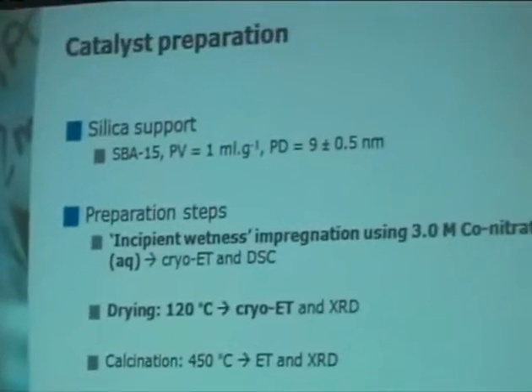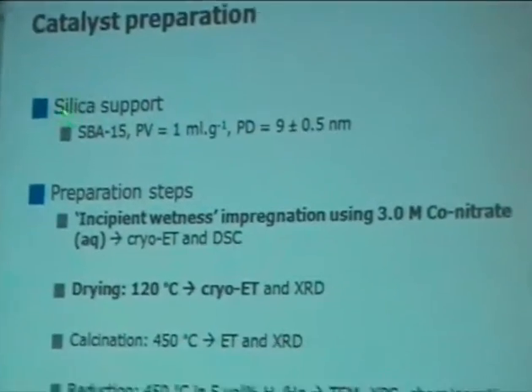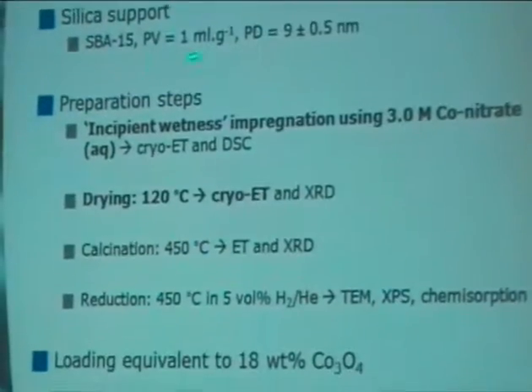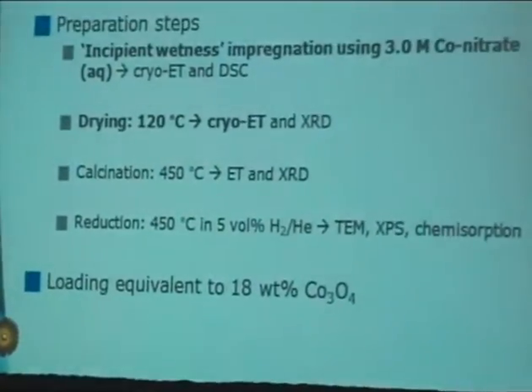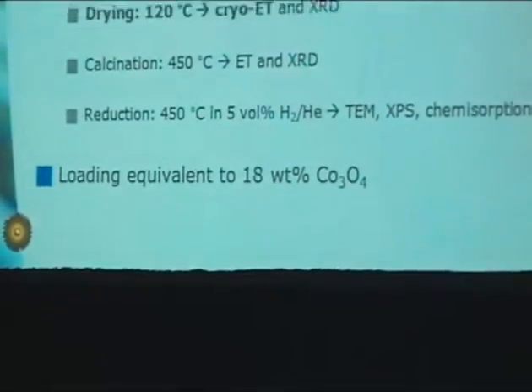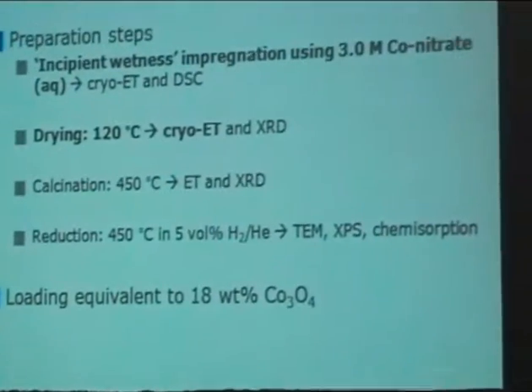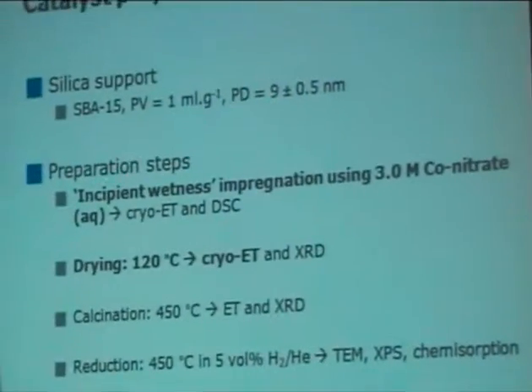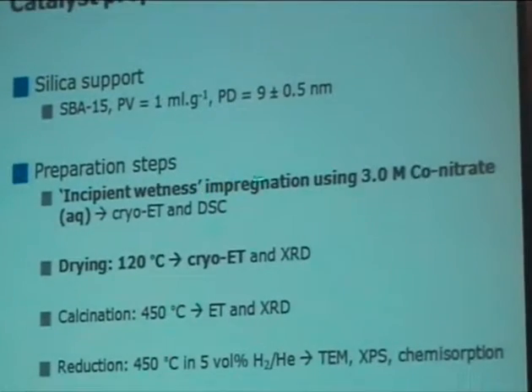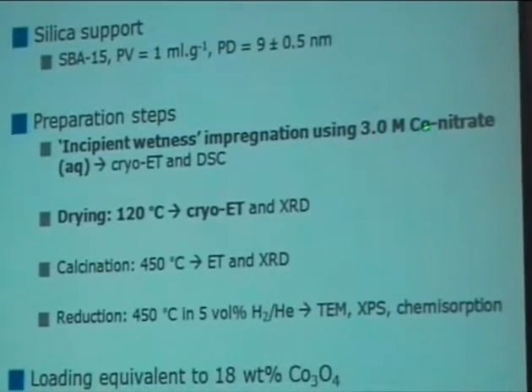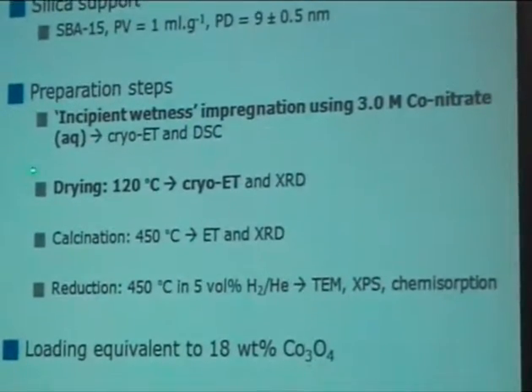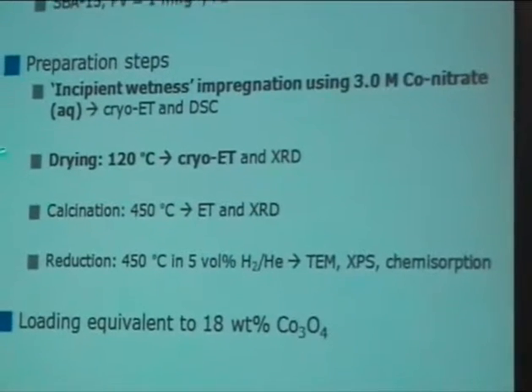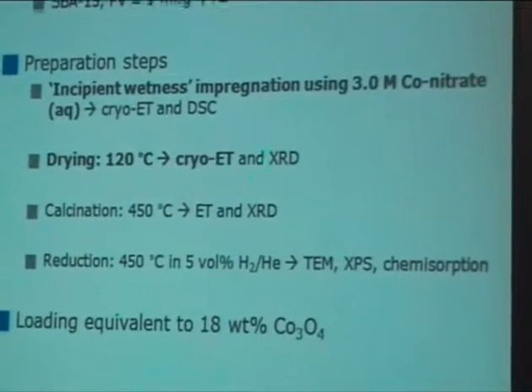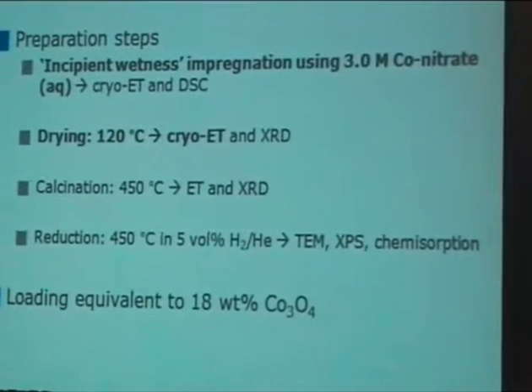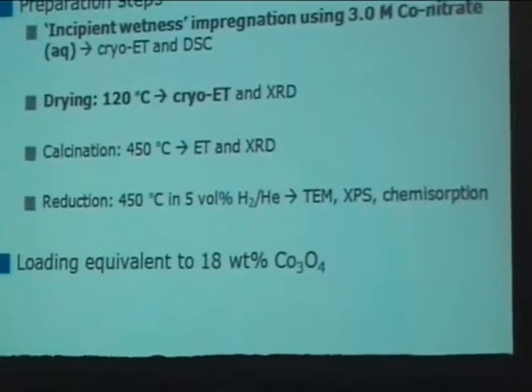Well, the catalyst preparation that we used in case of the silica support was that we first started with a model support, SBA-15, so the ordered mesoporous materials with this given pore volume and pore diameter of 9 nanometers. And we use an incipient wetness impregnation technique with a concentrated cobalt nitrate solution. I will focus after the drying step, where we apply cryo-electron tomography in order to prevent decomposition of the cobalt nitrate in the electron beam.